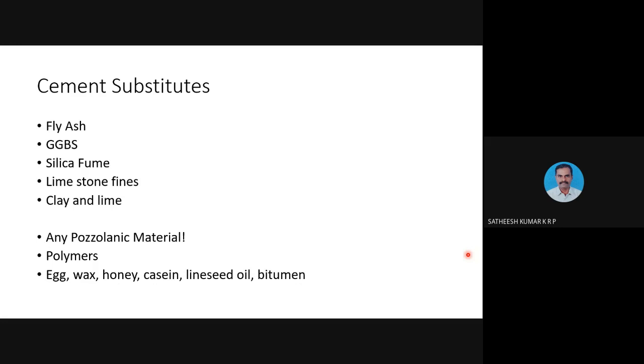This process is very common in Karaikudi, where we call the houses Chettinad houses, and they were using honey with a seed of a plant by the name Kadukkai, with lime. The lime was also in the form of hydraulic lime. The initial process was they used to prepare lime first, and lime was prepared from the shells, and this lime was prepared with fine sand as well as with marble dust, and this was used as the main ingredient for the mortar.